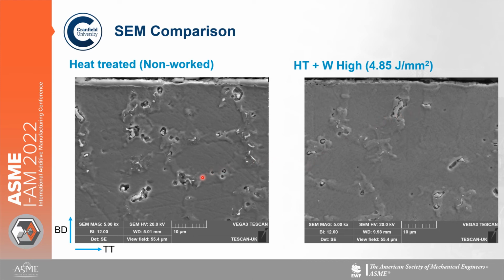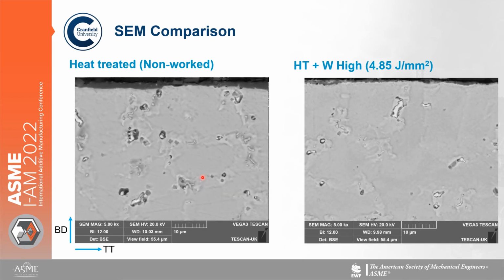And if we switch to backscatter, we can see our brightly coloured precipitates, indicating heavier elements in these precipitates versus these darker coloured phases. And they're virtually the same in both conditions.